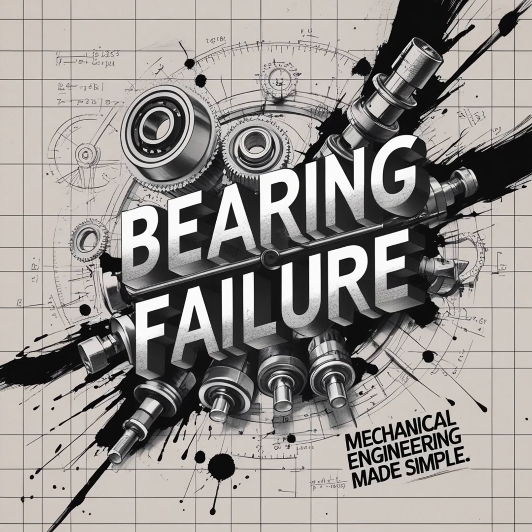So how does that happen? Well, corrosion often happens when the machine is idle because it allows the contaminants to pool in one spot. When you inspect the bearing later, you'll find these little damage spots, these etch marks, and they're spaced at exact intervals. Corresponding to the rolling elements. Exactly. The spacing matches the rolling element spacing. The simple fix for this is just to periodically rotate the shaft while it's idle, just to keep the surfaces wet and redistribute the load.